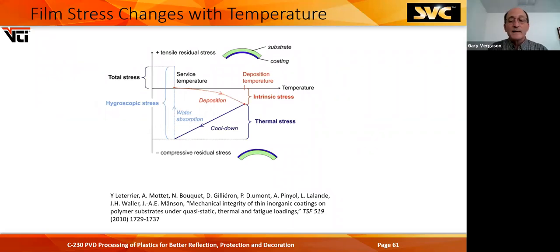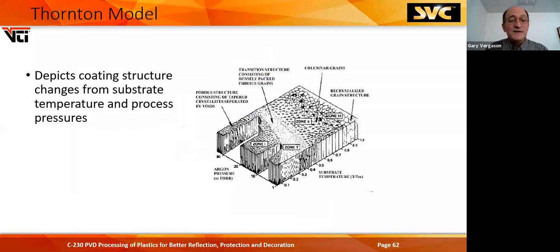For people that like fun graphs, this discusses the compressive and tensile stress that coatings build up. What more people are used to is the Thornton model, which depicts the coating structure changes from the substrate temperature and the processing pressures. So you can see that temperatures can widely affect the growth of the film and what the characteristics of the film are. We're looking for films that are lowly stressed or properly stressed. In some cases, the use of the part gets heated up quite a bit, and the coating's got to be able to expand with the part and then contract with the part and not crack. And it takes a little bit of effort.